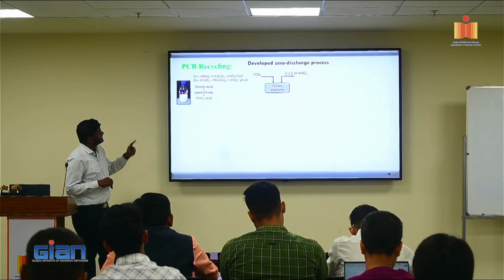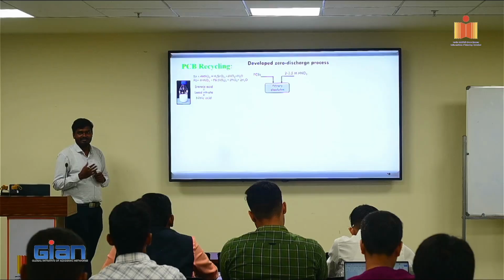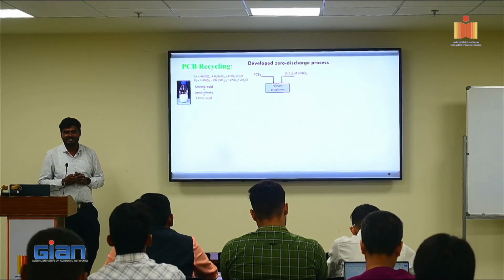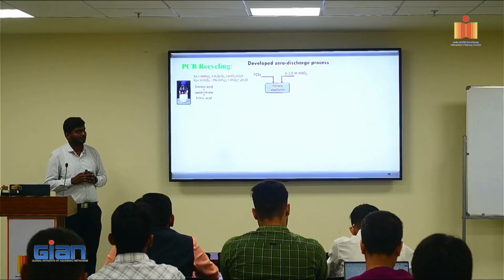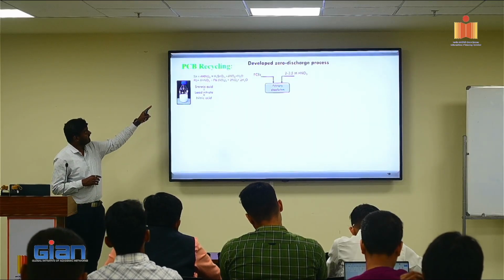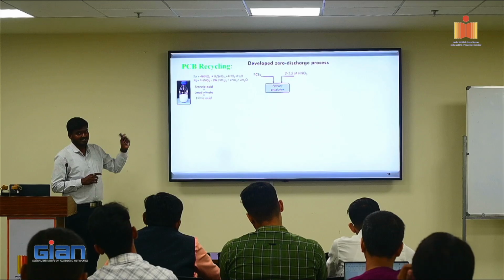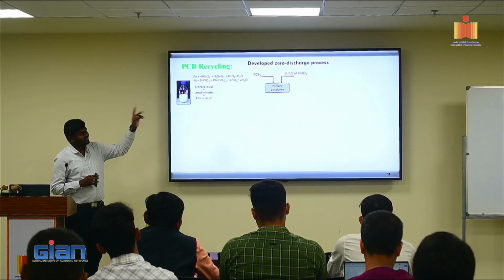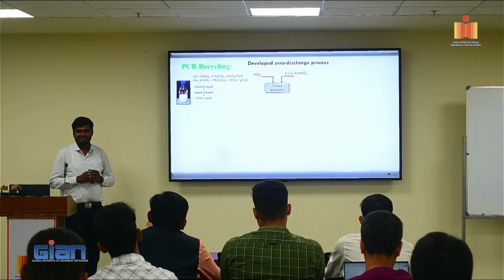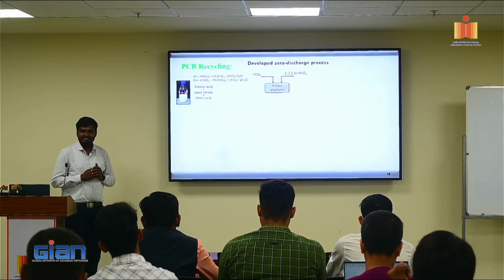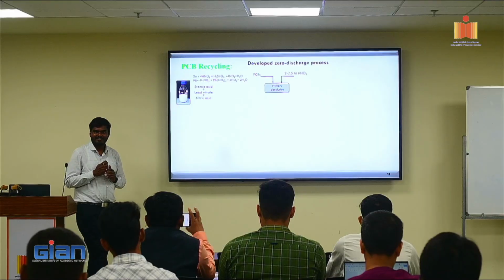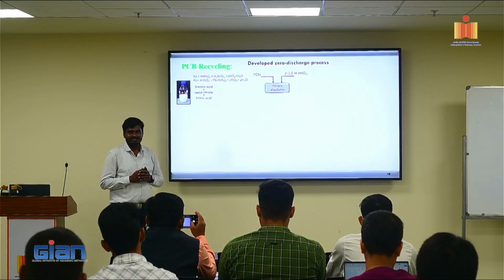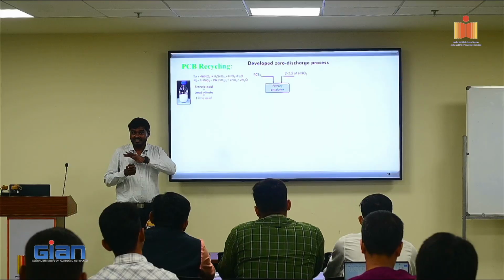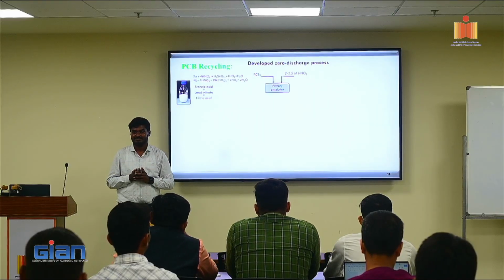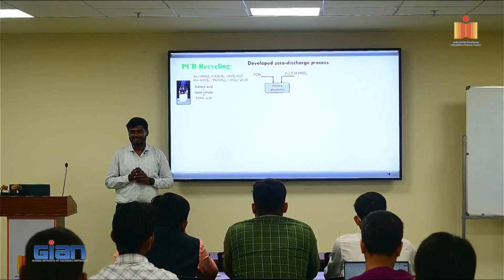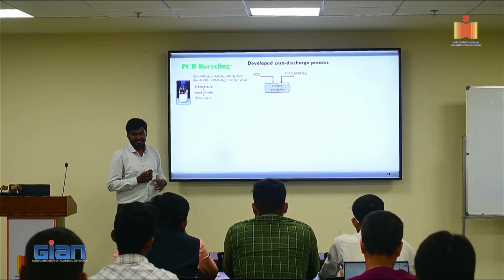Once you do this, you can see that tin reacts with nitric acid and forms the hydrated form of tin oxide, H2O.SnO2, which is a precipitate. And lead reacts with nitric acid and forms lead nitrate, and NO2 gas is released. I didn't write the reaction with copper because the rate of reaction of copper, when the acid concentration is less than 2.5 molar, with the resistance of the epoxy layer is very slow. No copper gets reacted at this condition. Only tin and lead get reacted.